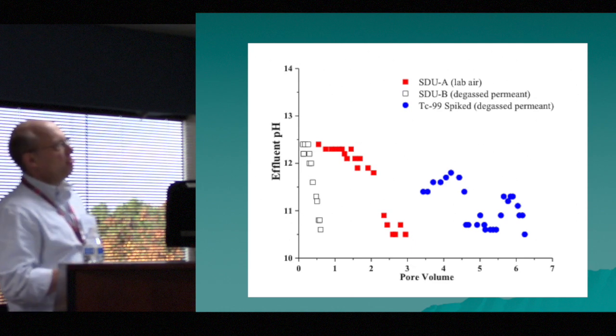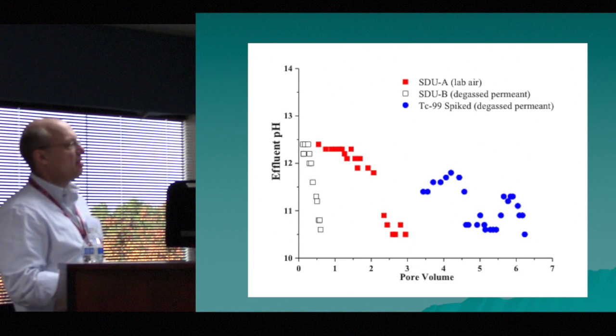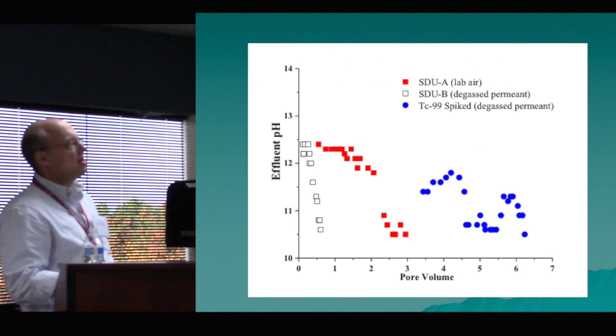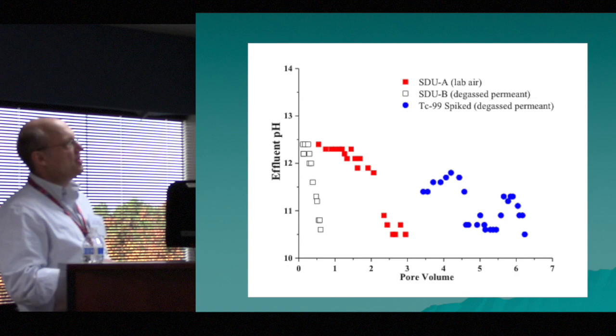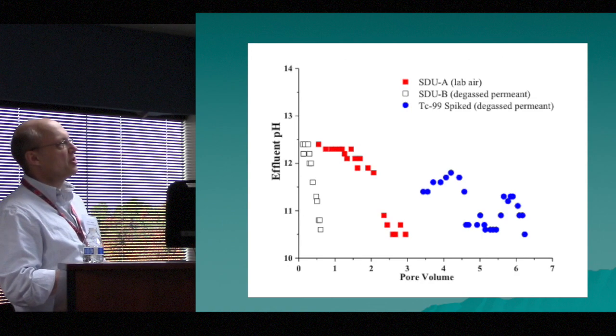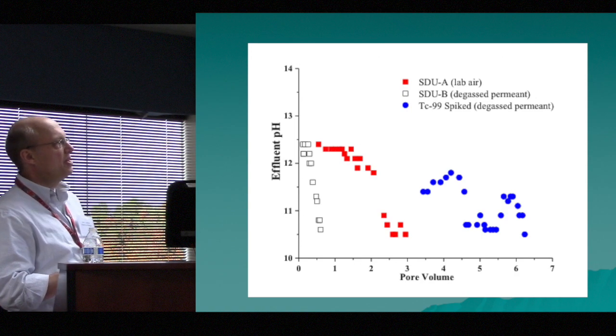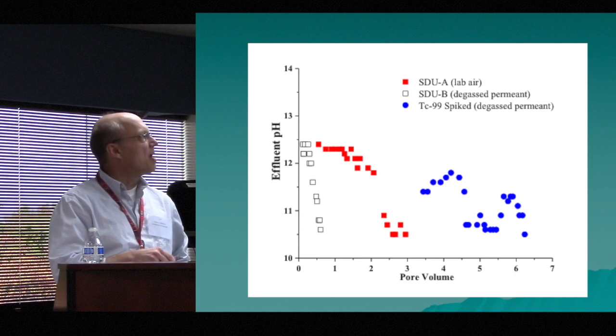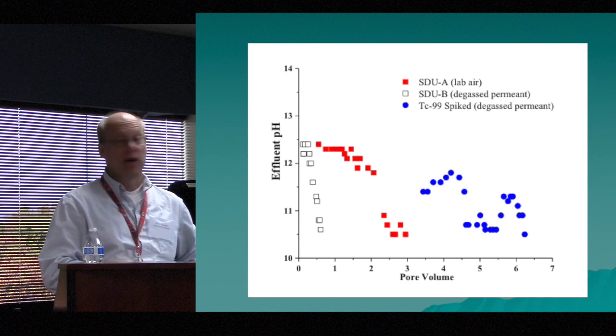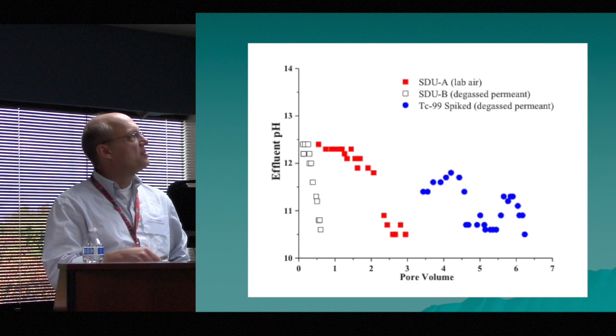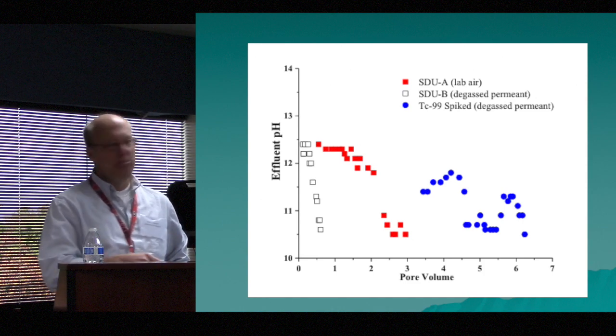This is the effluent pH of 3 different samples out to 6 pore volumes. For the 2 SDU samples, we see them starting out at about 12.5 and going down very, very quickly. For the Tc-99 spiked samples, we have it going down, and we're missing data up here.